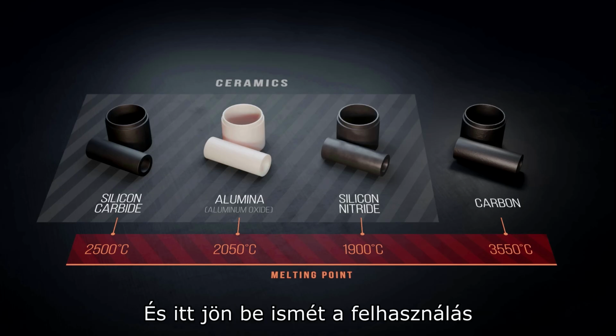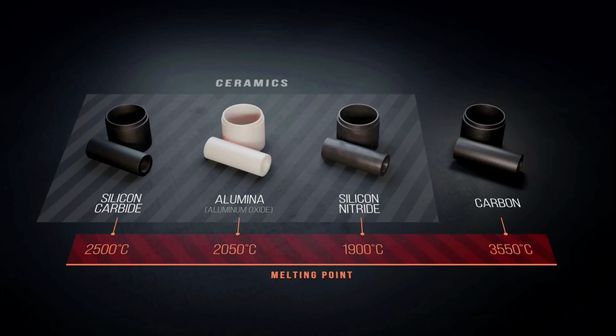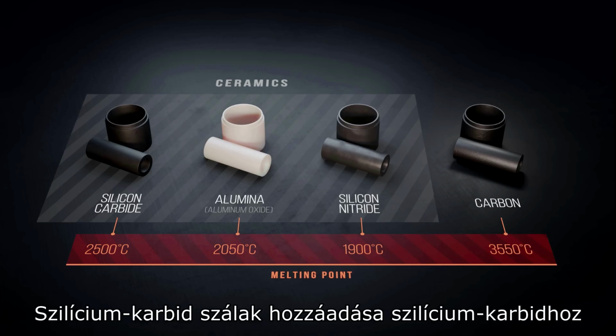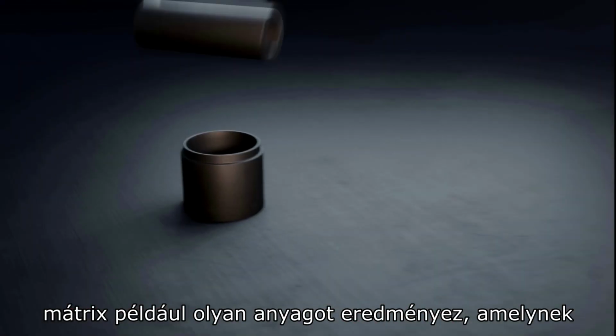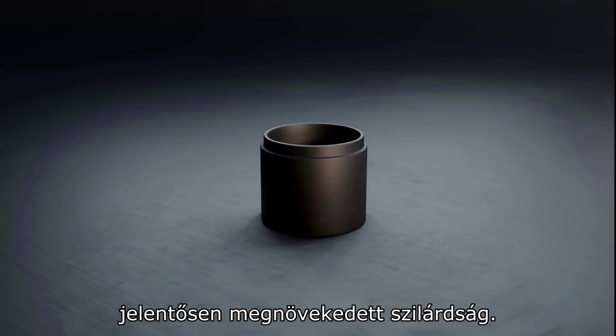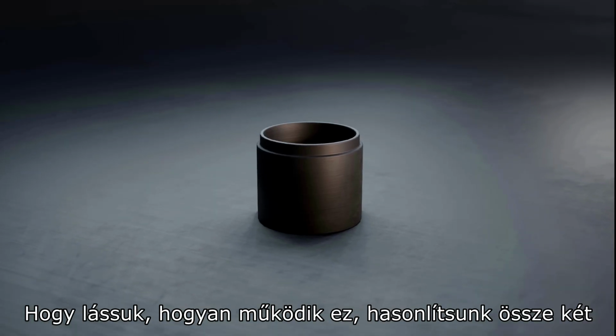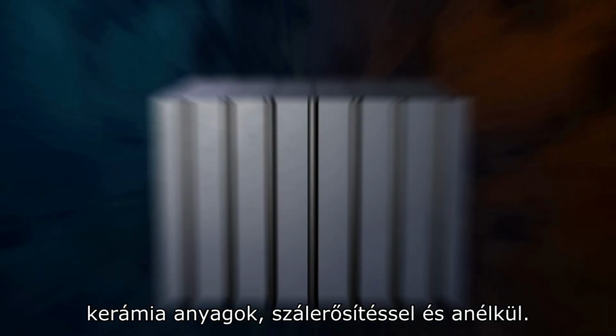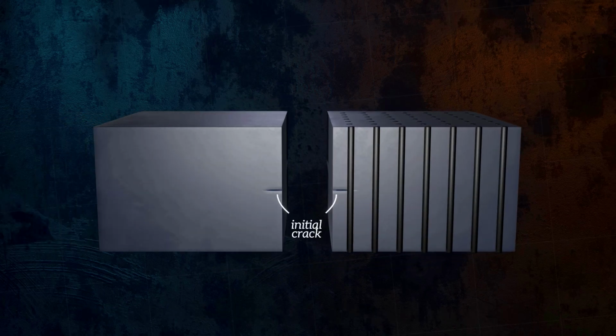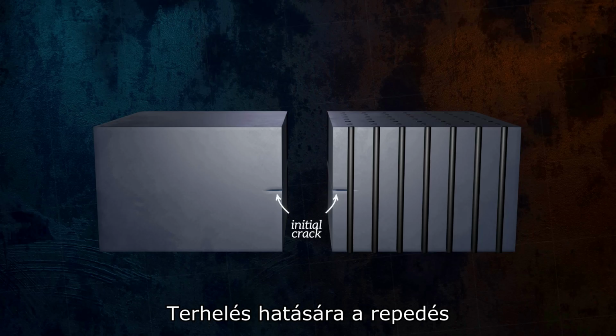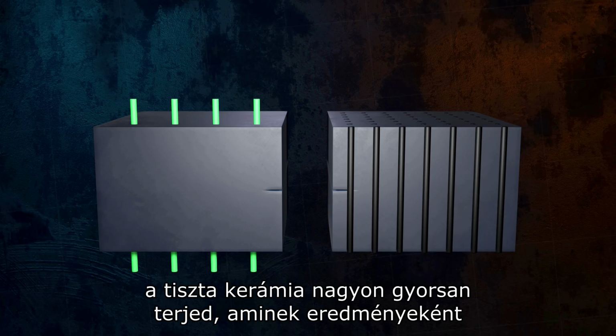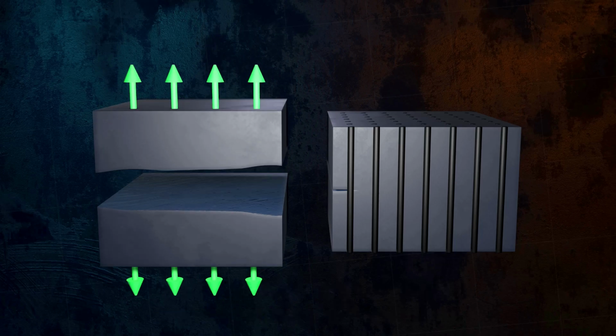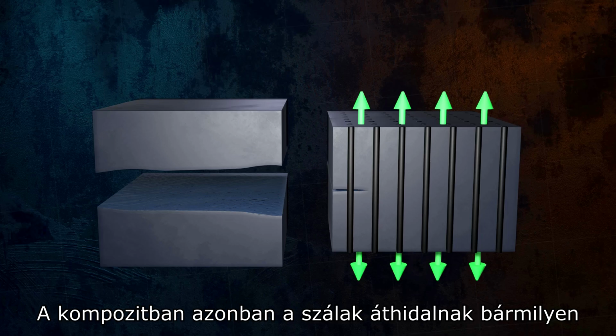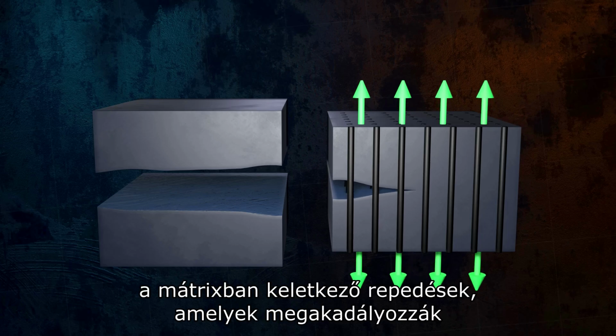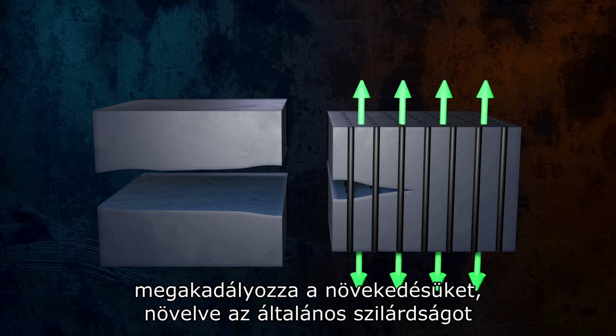And this is where, once again, the use of composites can make a big difference. Adding silicon carbide fibers to a silicon carbide matrix, for example, results in a material with significantly increased toughness. To see how this works, let's compare two ceramic materials, with and without fiber reinforcement. Both contain an initial crack. When a load is applied, the crack in the pure ceramic propagates very quickly, resulting in failure of the material. In the composite, though, the fibers bridge any cracks that form in the matrix, which prevents them from growing, increasing the overall toughness of the material.